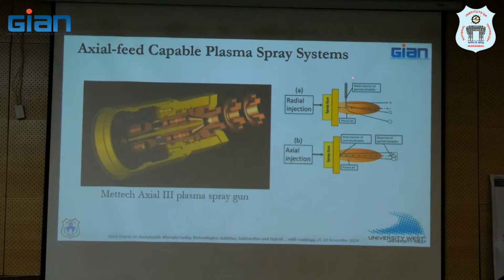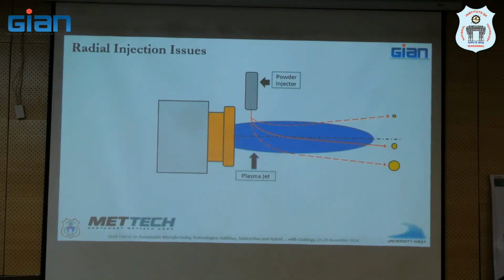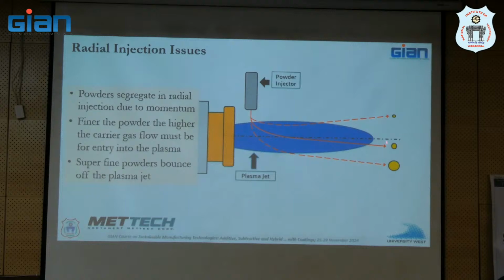To overcome that, if you increase the carrier gas flow rate, some of the heavier particles, just because of density, go right through. So you then need a very precise window for the right kind of particles to go through the center. Instead of that, if you can inject it axially, like here, then everything works well. Your thermal energy is used up fully, your particles travel in a manner that you would want them to travel, and that leads directly to higher deposition efficiency. So this is also something which is very new in plasma spraying. I'm showing the same problem in a magnified sort of way. There is segregation of powders that happens. You need higher carrier gas flow if these kind of particles need to come through the center, and then beyond a certain particle size, you cannot do anything.